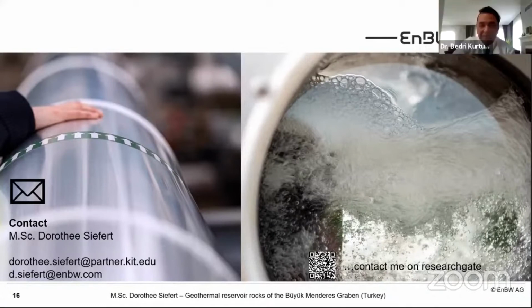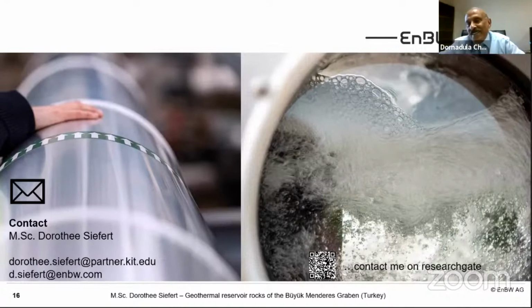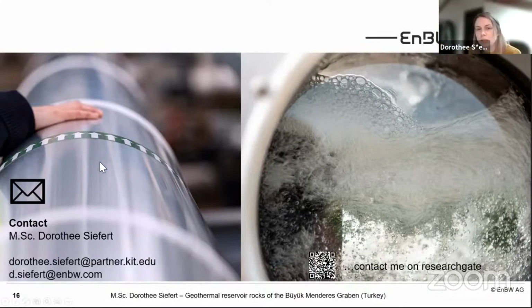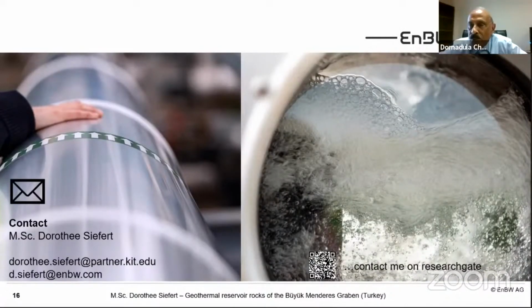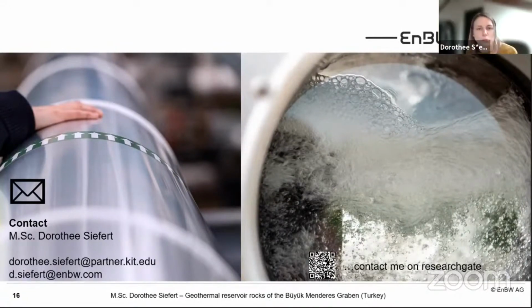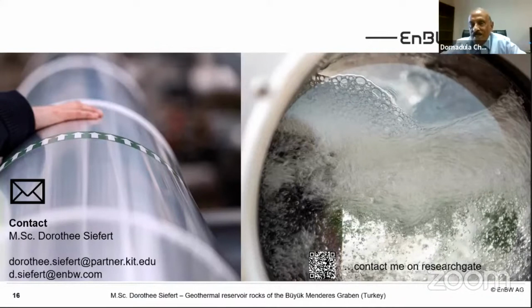Yes, please, Professor. Dorothee, it's very interesting data and presentation. I really like it. You have a lot of information there about the seawater composition of the Paleoseas actually during Tethyan. Am I right actually? Especially the cerium negative anomaly and yttrium positive anomaly, they are very, very significant actually. Does it mean that these are the proxy of Paleoseas actually? I would say so. That's what we concluded. And it's quite pronounced, the cerium negative anomaly, and also sometimes the yttrium anomaly is strong. You don't see that in the modern sea actually.